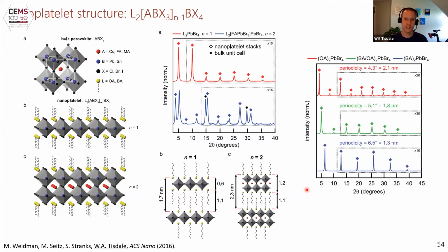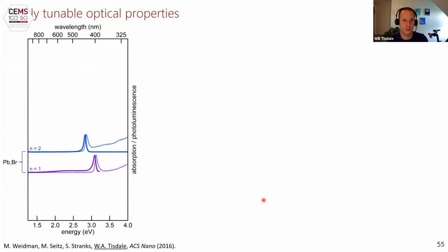You can control the spacing by controlling the ligands that are on the surface of these nanomaterials. And you control the band gap or the exciton energy by controlling the composition of the material.